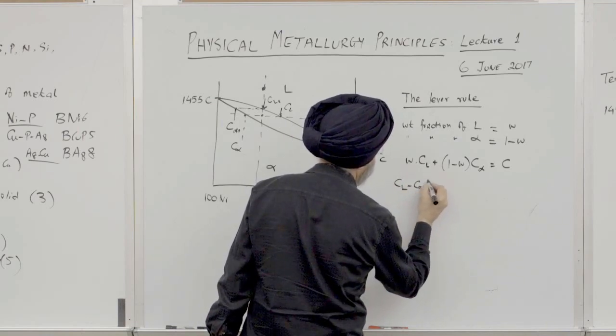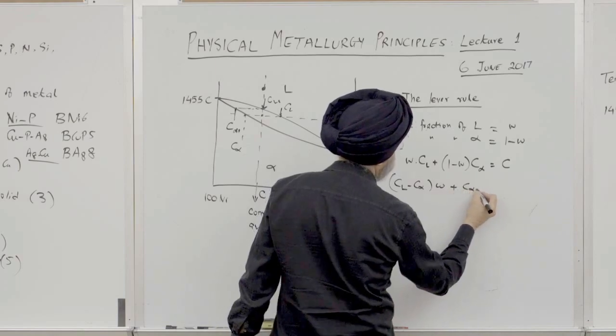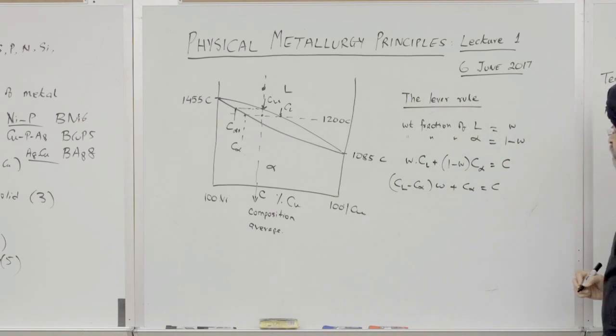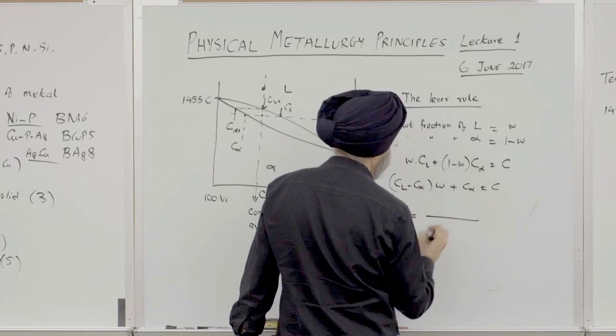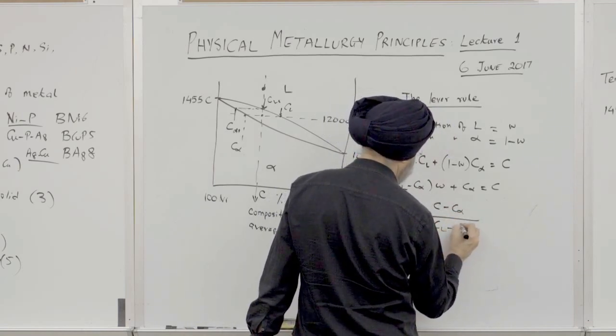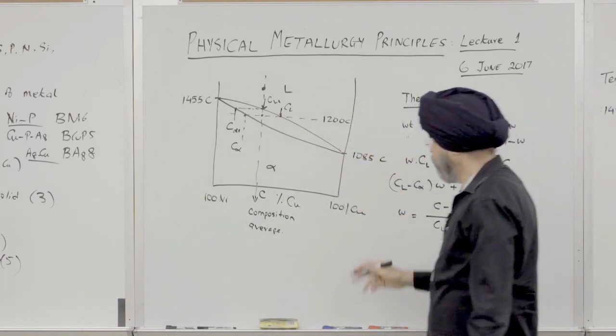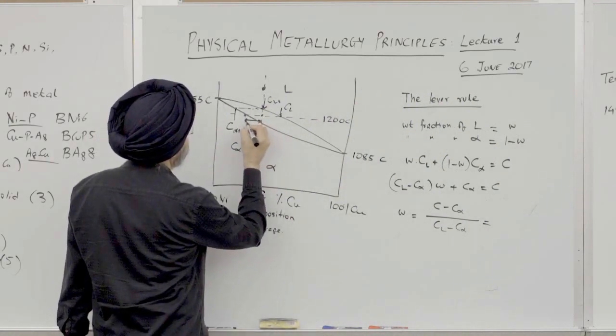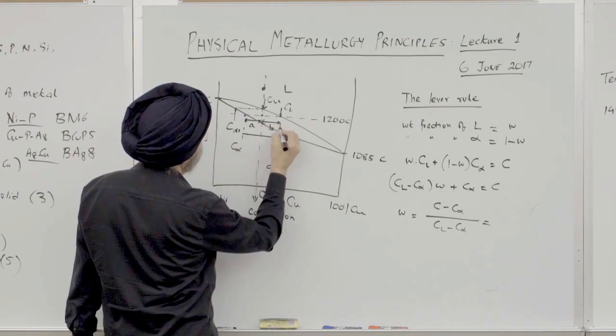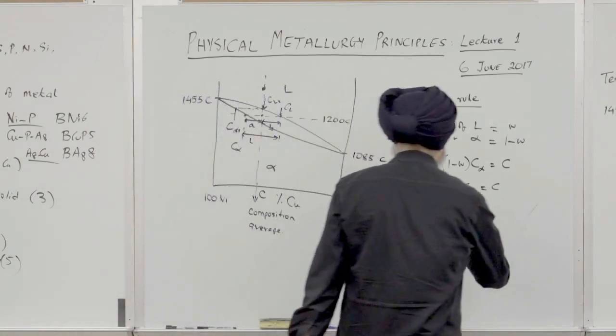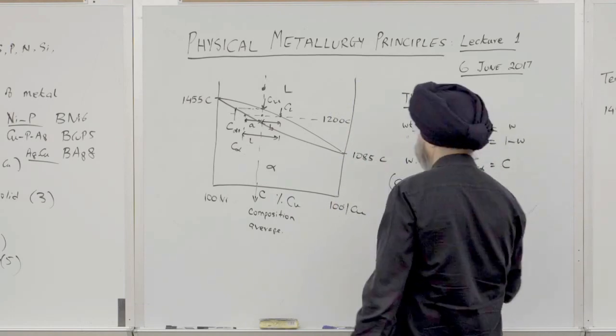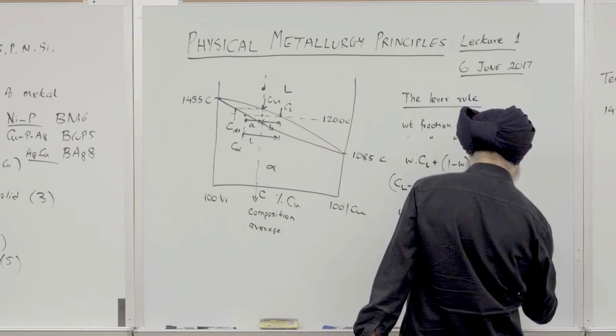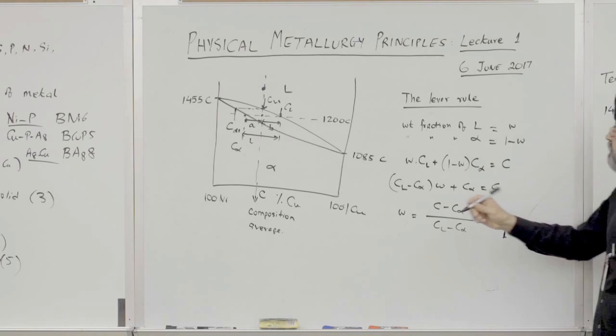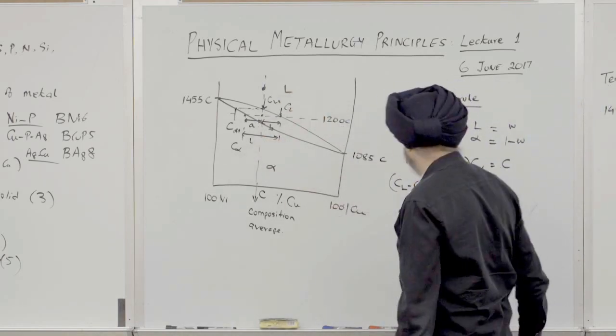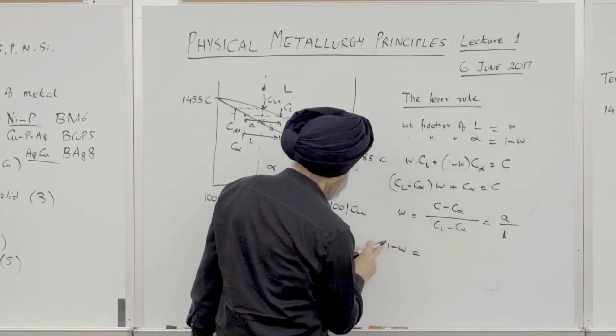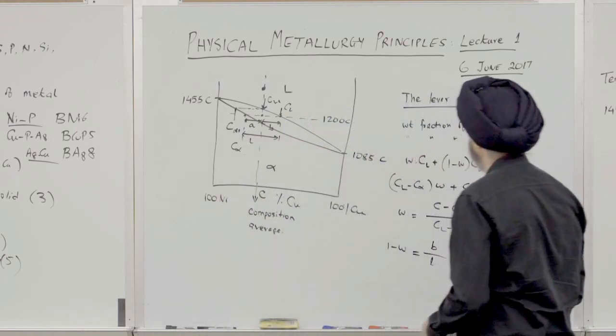So now let's collect the W term. Cl minus C alpha times W plus C alpha is equal to C, right? So W, the weight fraction of the liquid, is C minus C alpha over Cl minus C alpha, right? So let's look at this diagram over here. To keep life simple, I'll call this A, and I'll call this B, and the total, we'll call it L. So C minus C alpha is A, and Cl minus C alpha is L. So the weight fraction of liquid is just A over L at that temperature. And the weight fraction of the solid is B over L. So this is called the lever rule.